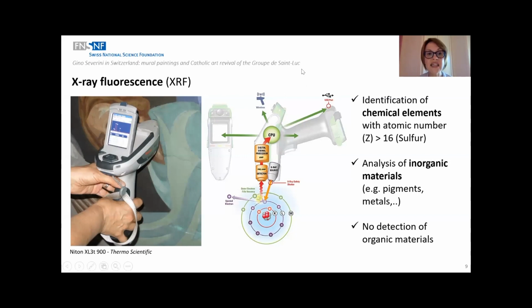In particular, with this instrument reported in this picture, produced by Thermo Fisher, it is possible to obtain information about chemical elements with atomic number higher than 16, equal to the number of sulfur. Therefore, with this instrumentation, it is possible to analyze inorganic materials, for example pigments and metals, but it is not possible to obtain information for the organic materials composed of carbon, hydrogen, and oxygen.